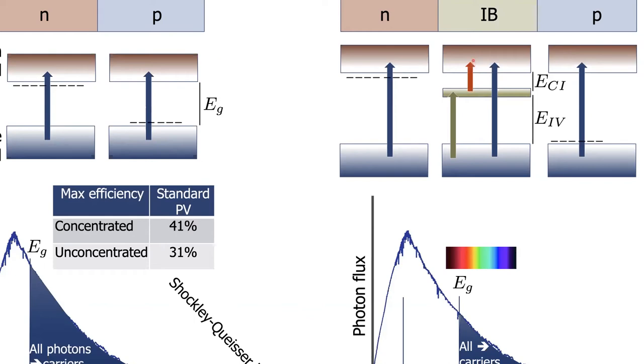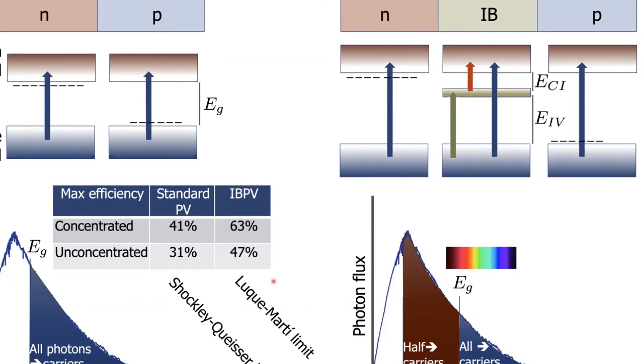lower energy photon to move that electron up to the conduction band. We can then get the current out and ideally set our voltage by this larger band gap than we have over here in the Shockley-Queisser limit. So this allows us to turn a larger portion of the spectrum into current at a higher voltage. And using the same kind of techniques that Shockley and Queisser did, Luque and Marti in 1997 showed that in each case, concentrated and unconcentrated light, we could in principle get 50% higher efficiency.